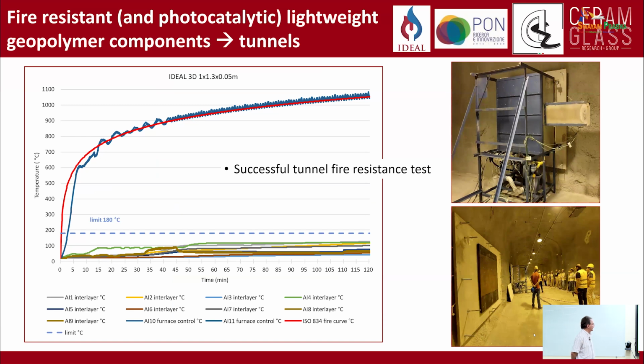We carried out a successful tunnel fire resistant test. And in order to be successful in this test, we needed to follow a certain heating curve, and the temperature measurement on the other side of the board should not have exceeded 180 degrees. And here you can see the experiments that were carried out in a road tunnel in Crete, in Greece. This is the furnace with all the controls for the temperature. This is the part that was 3D printed and attached to the wall of the tunnel.